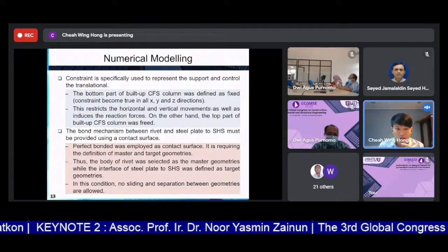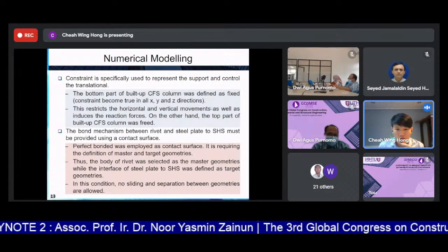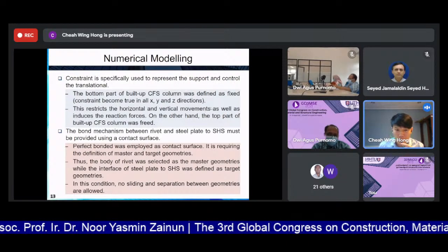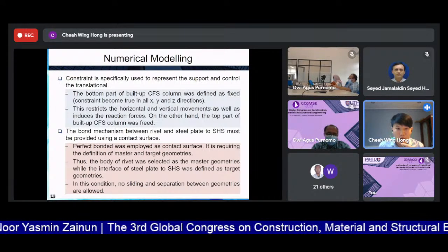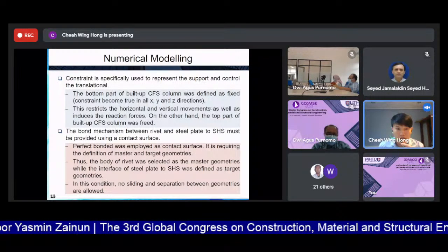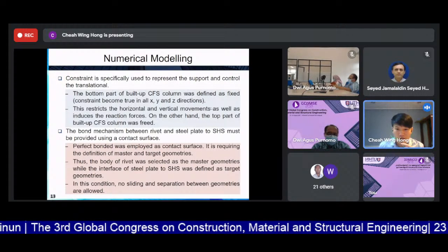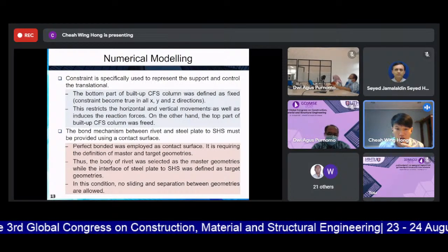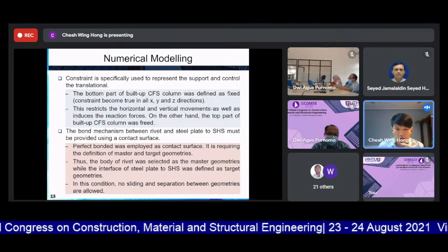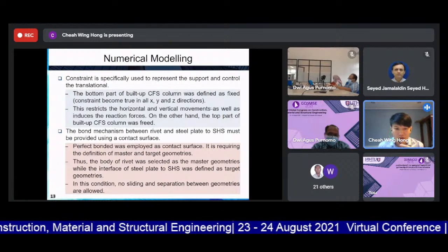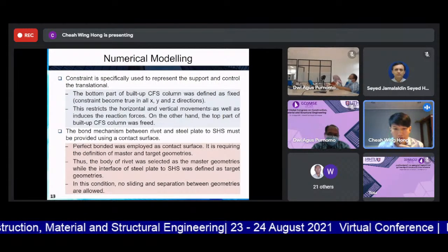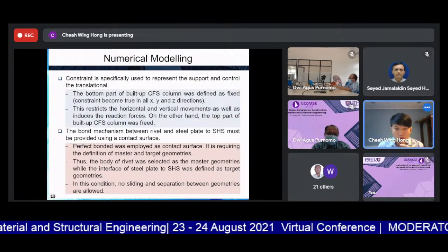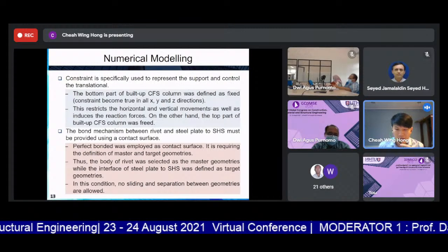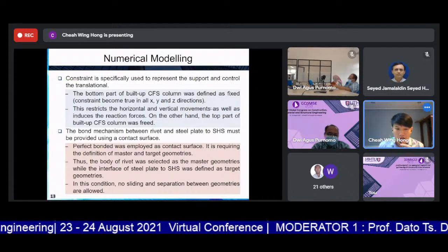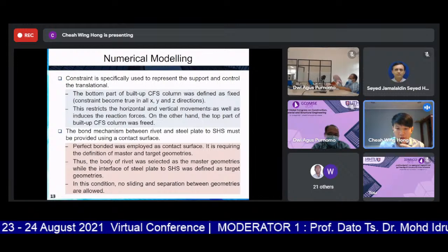The bond mechanism between the rivet and steel plate to the SHS must be provided using the contact surface. In this numerical modeling, perfect bonded was employed as the contact surface, which requires the definition of the master and target geometries for the built-up CFS column. Therefore, the body of the rivet was selected as the master geometry, while the interface of the steel plate to the SHS was defined as the target geometry. In this condition, no sliding and separation was allowed between the geometries.